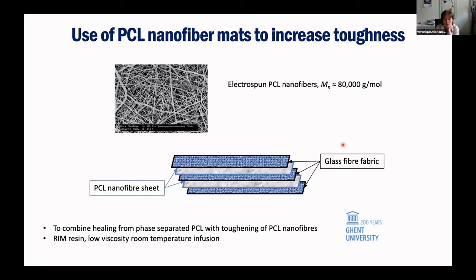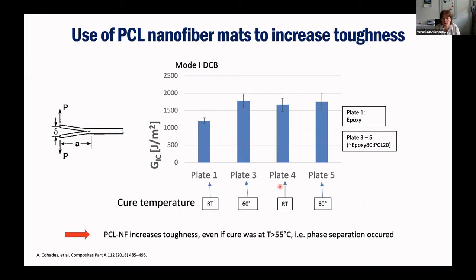And then we wanted to see what happens. So there we used a resin with low viscosity, a room temperature infusion, because we didn't mix the PCL directly into the mixture, but we had the PCL here and we infused with a pure resin. And we used the RIM, which they used a lot in the lab. What we saw was very interesting. So if you look at the plates, plate one is the pure epoxy reference RIM plate. We had a G1C of about 1,000 and so on, which was what we expected for this material.